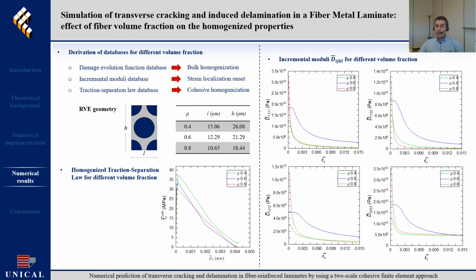The previously mentioned offline computations have been performed for deriving three different databases. That is, a damage evolution function database for bulk homogenization, an incremental moduli database for the detection of strain localization onset, and the traction separation law database for cohesive homogenization.